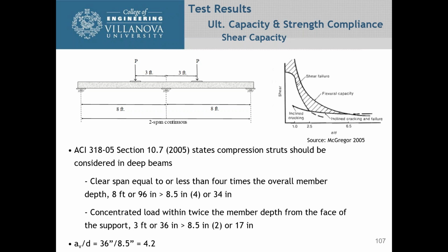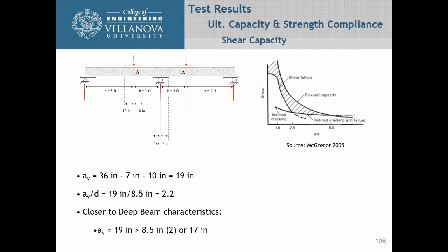So what we want to look at is ACI 318 section 10.7, which says that compressive struts should be considered in deep beams. And what are we looking at as a deep beam? Well, the clear span is equal to or less than 4 times the overall depth of the member. So 8 feet or 96 inches has to be greater than 8.5 times 4 or 34 inches. So it doesn't agree, but the concentrated load is within twice the member depth from the face of the support, or 36 inches or 17 inches. So for both of those, we really can't consider it a deep beam.